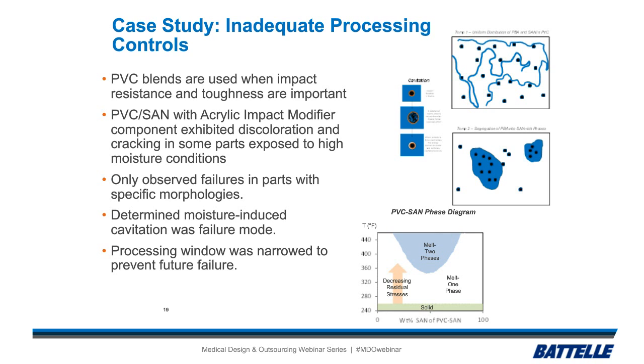The middle picture there with the blue dots shows that the domains are separated. And the problem with the domains being separated is it allows water to be able to get into this material and cause moisture-induced cavitation. So it's very important that the mixing occurs in one phase. And when we looked into this some more, we found that the phase diagram for the PVC SAN was that bottom image. And at higher temperatures, we got two phases in the melt when this was being mixed together. And that caused the problem. So we don't want two phases. We want a nice homogeneous mix.